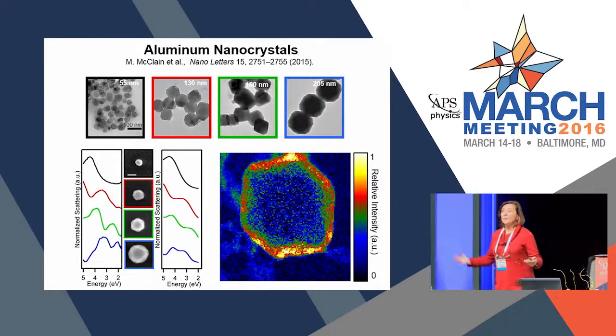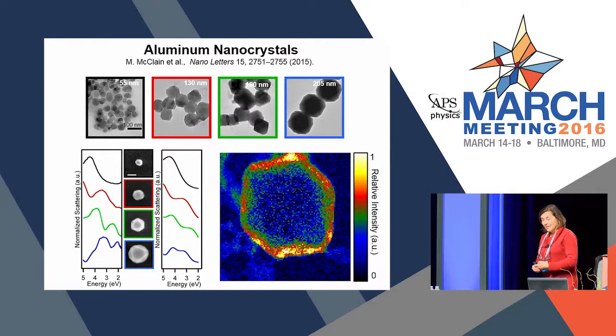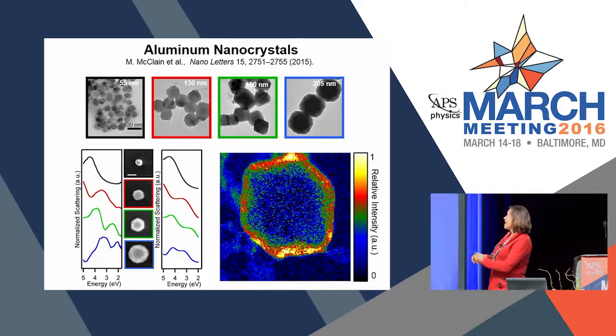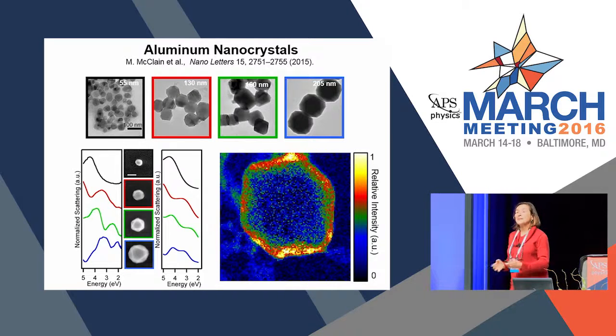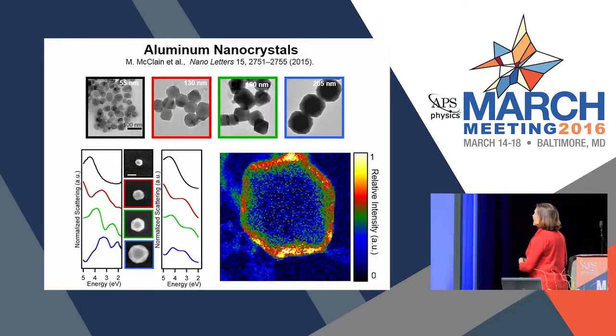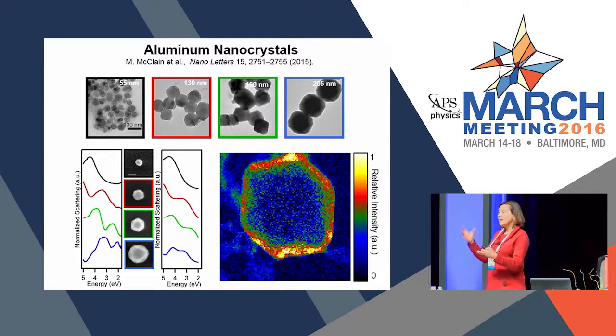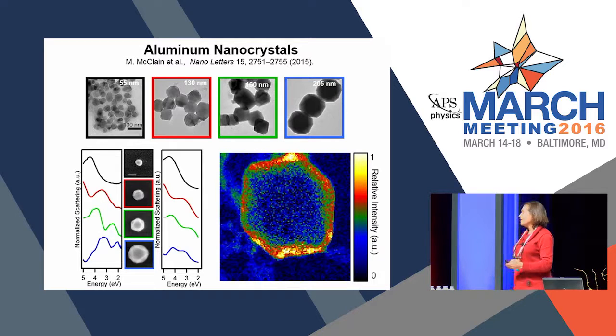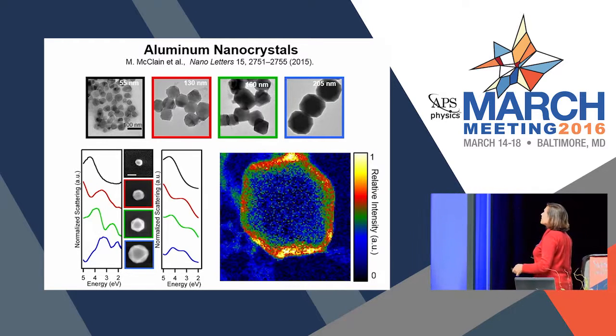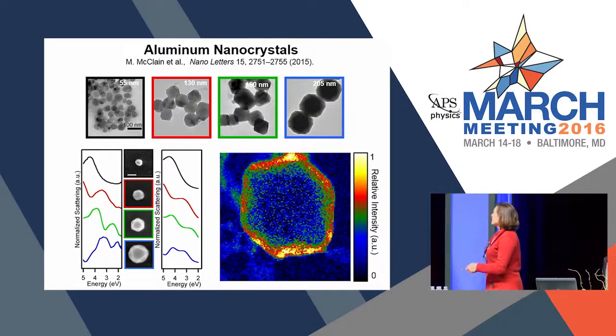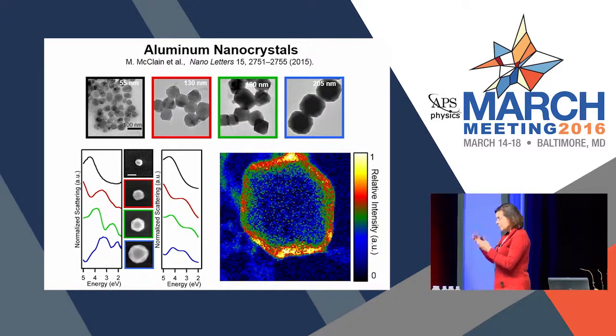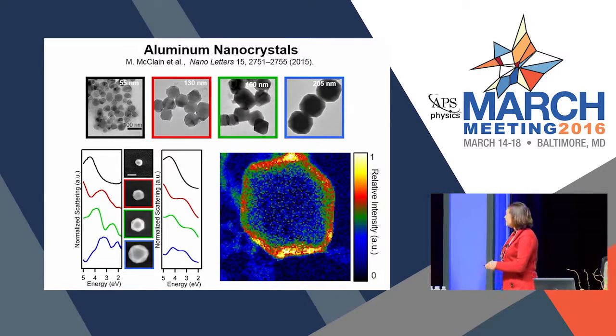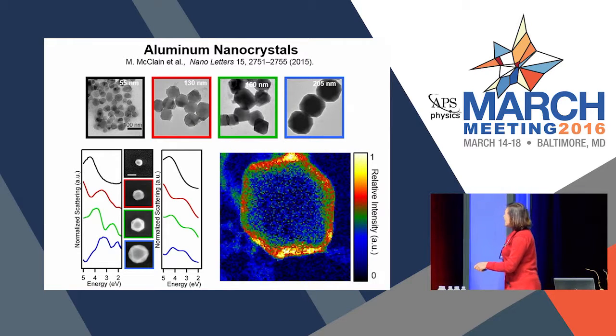So I mentioned aluminum. Well, as I said before, gold nanoparticles are quite interesting and have this plasmon resonance, but so does aluminum, and aluminum is in principle much, much less expensive. And so we've developed a way to make, in analogy with colloidal gold, colloidal aluminum nanocrystals. They're beautiful faceted structures. We can control the diameter of these structures, and we can look at the scattering spectrum of the individual nanoparticles, so we can see the size-dependent resonance, but we also see something quite interesting.